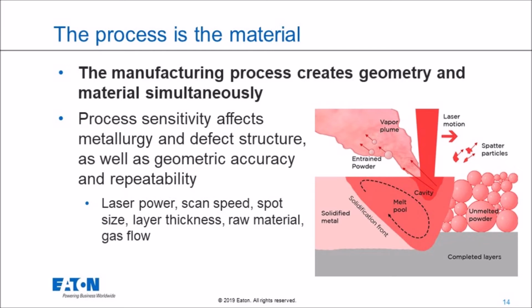I don't have this on here, but in some of the more recent papers coming out of, I think, Lawrence Livermore National Labs, they have a synchrotron, and you can see this process happening in real time in slow motion. And it's very chaotic. So the question is, how do you make sure that this happens the same way every time? And it comes to process sensitivity. What that means is, for example, if the laser power changes by 1%, what does that mean for your process? Does that mean it's a bad part? Can you deal with a 1% change in laser power? And can you do that for scan speed, spot size, layer thickness, raw material, and gas flow? Controlling all of these individual inputs into the process becomes critical to make good parts repeatably.